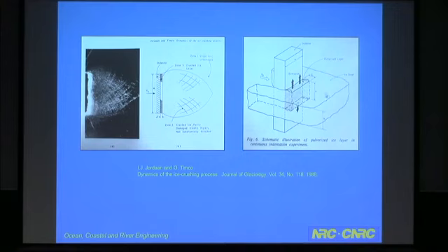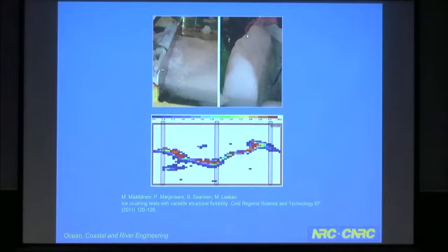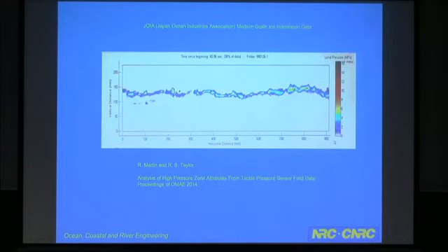And this idea has persisted to today. There are some people that still view things this way. However, if in those tests they had been able to look edge on to the ice, like in these tests that were conducted by Määttänen and his colleagues, they would have seen that the ice takes on a shape when it's in contact, like the mountain peaks as Kai referred to them, but the actual contact is more central.